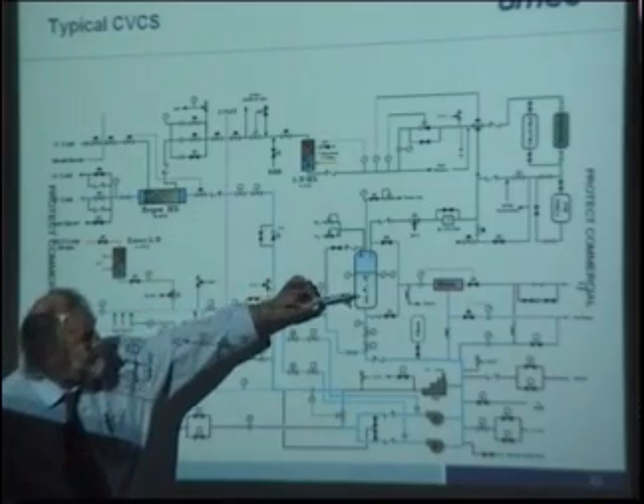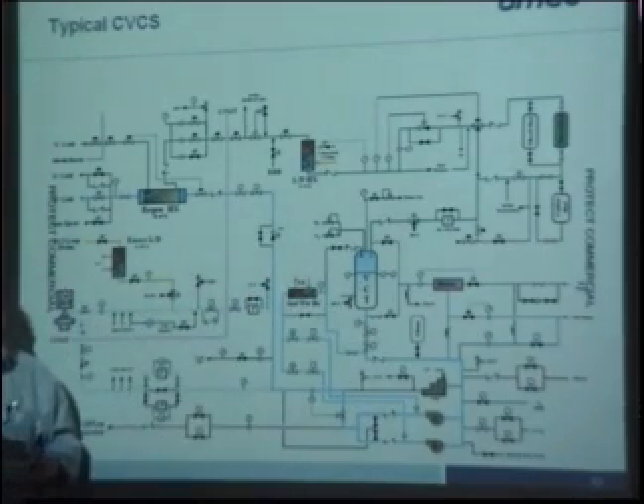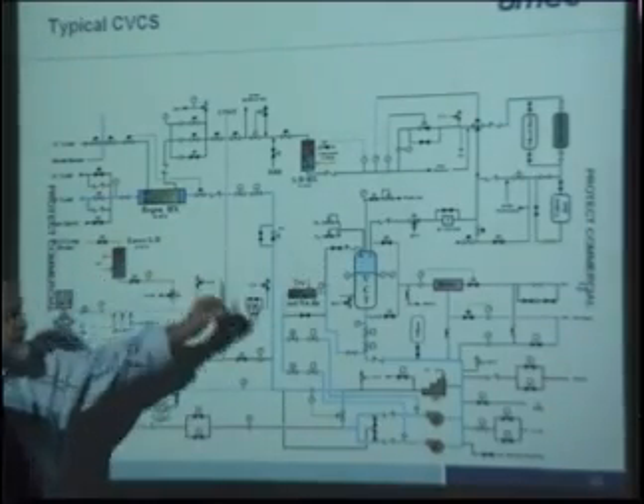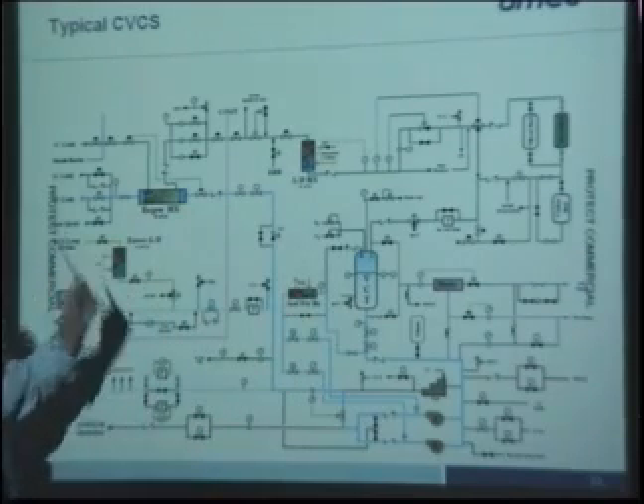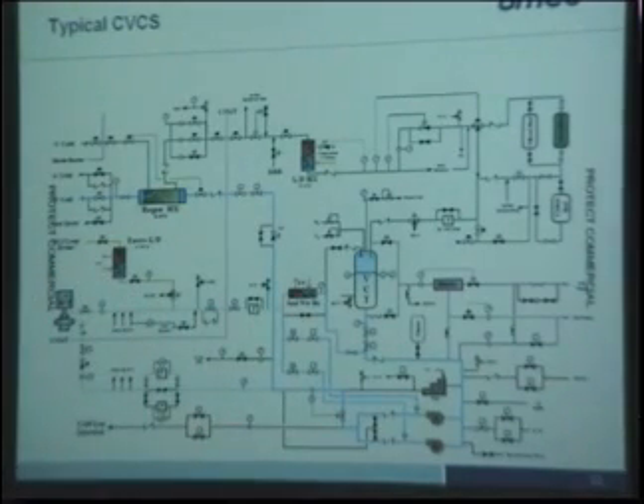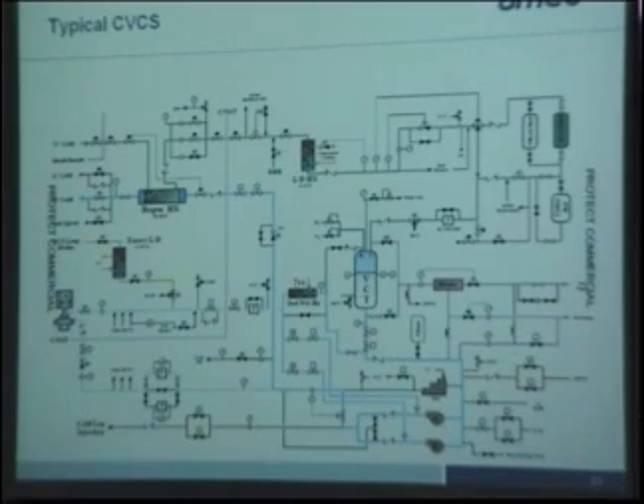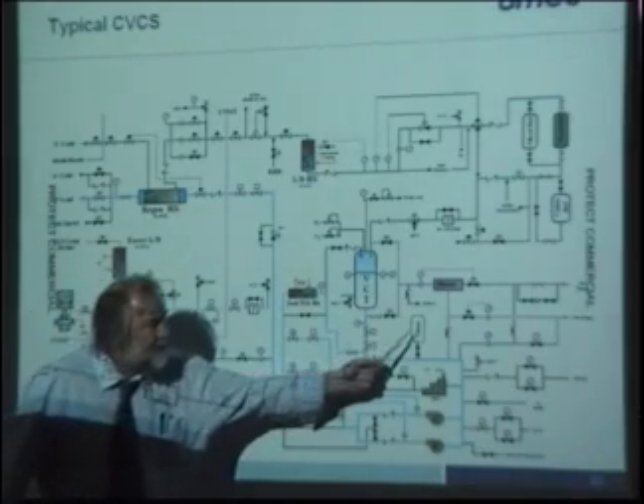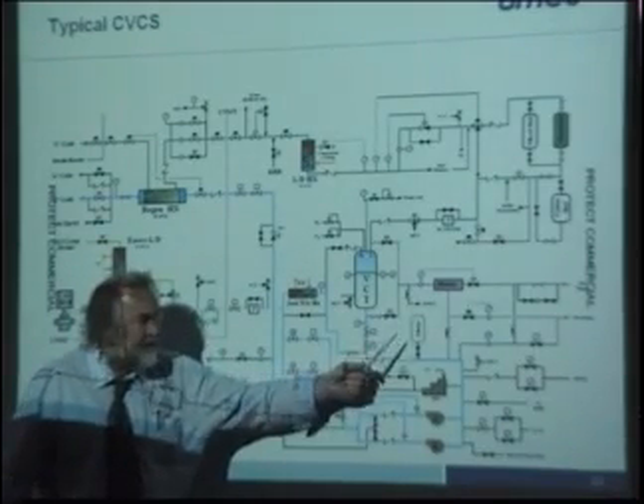The volume control tank is there firstly to maintain the hydrogen concentration. That operates with a hydrogen overpressure there, about 2 bar. And also, because it's flushed out with hydrogen all the time, you're taking out all the fission gases, all the xenons and kryptons, and that goes off to the gas waste reprocessing plant. You also have a filter as well in here for particulates. So then the main features of how you control are, I should mention the chemical dosing tank. You put your lithium hydroxide and hydrazine, hydrogen peroxide in the chemical addition tank.